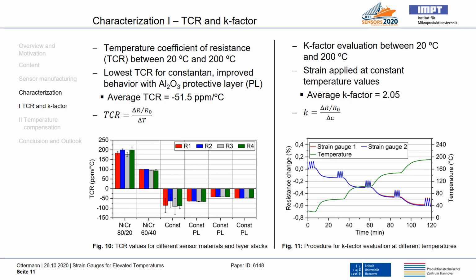Therefore, the temperatures increase stepwise, as shown in Figure 11 with the green curve. On the left y-axis, we can see the resistance change of two strain gauges with the red and blue curve. At constant temperature values, for example at 60 degrees Celsius, 3 cycles of strain are applied. They lead to a significant resistance change, as we can see 5 times in the diagram.